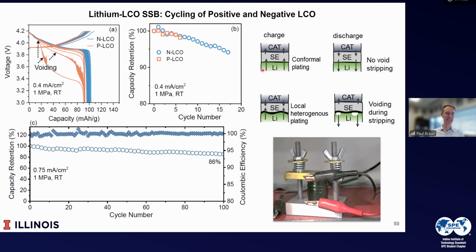And here just shows we made a simple cell. This one failed. The reason there's only 5 cycles is because after that, the capacity went basically to 0. You can see it falling here. This is the negative LCO, and it continues to cycle. And when we cycle this under a little bit less aggressive conditions, you can see here that we have 86% capacity retention after 100 cycles.